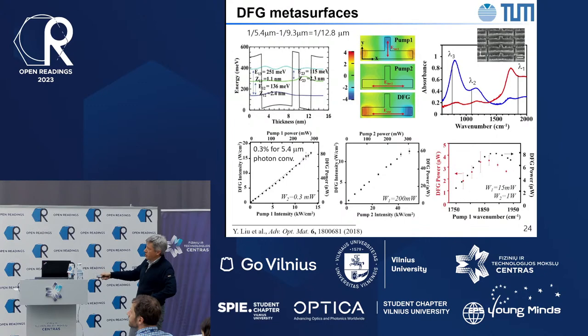And we could generate difference frequency generation here with a conversion efficiency of 0.3%. So 0.3% of the input photons at 5.4 microns are converted to the 12 micron radiation. And this is the dependence of the difference frequency generation versus pump 1, which was the 5.4 micron power, and this is the dependence of the difference frequency generation on pump 2. So we actually see very little saturation, and we have basically linear dependence of the output on the input. And this is the spectral dependence. We could tune the input, and we get difference frequency generation across the entire spectral range, but some wavelengths work better than others, and these are the wavelengths for which the antennas and the quantum well systems are resonantly enhanced.